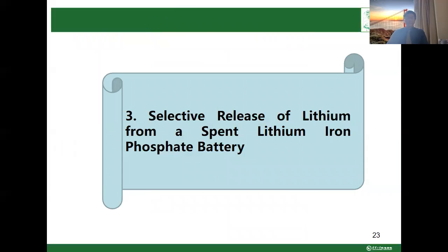In this chapter three, we mainly introduce one of our research works. The case shows how to use the mechanochemical method to realize the recovery of valuable metals in spent lithium-ion batteries. The experimental material we used was a spent lithium iron phosphate battery. Our research goal is to achieve the selective extraction of lithium from spent lithium iron phosphate cathode material through mechanochemistry-assisted solid phase oxidation.